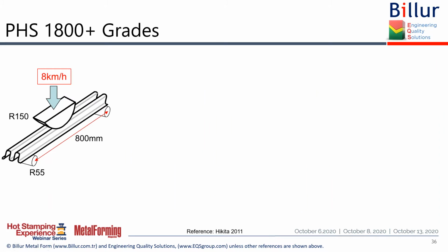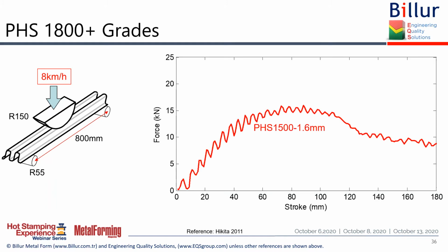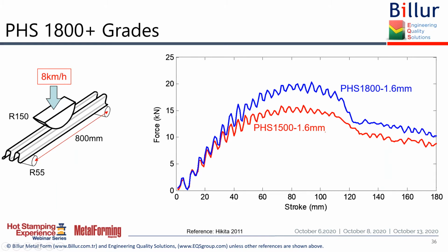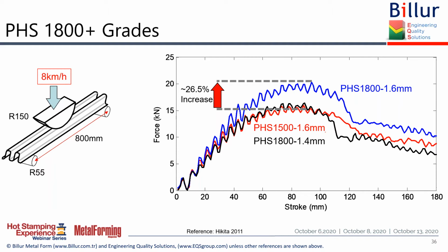Speaking of PHS 1800 and more, this is the bumper beam from Mazda CX-5. This is an almost 10-year-old technology now. If you had 1.6 millimeter thick PHS 1500, this is the force versus stroke you would get. Here you see the PHS 1800 in the same thickness level. You would have about 25% increase in the peak force. And with the black now you're seeing PHS 1800 in 1.4 millimeters. So we could save about 12.5% by down gauging.